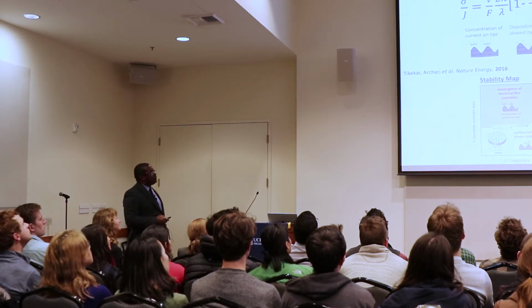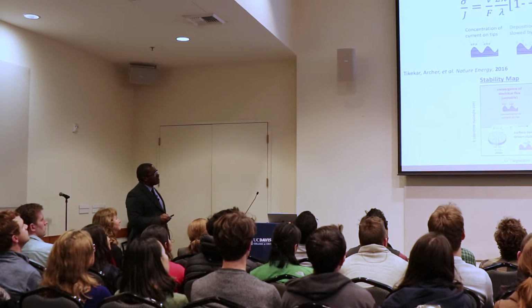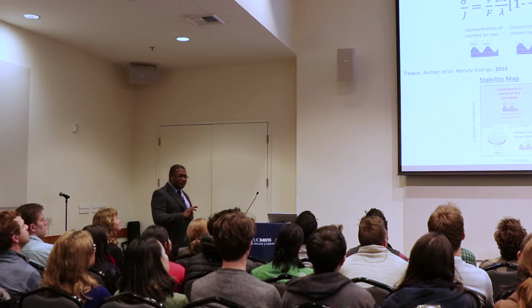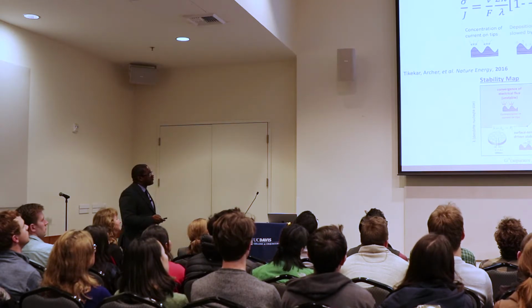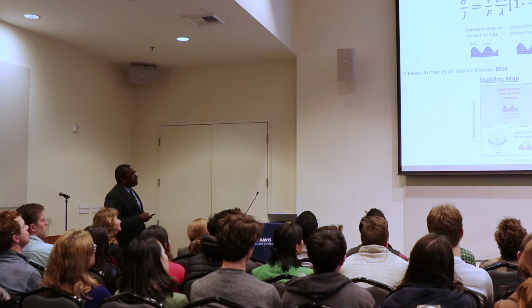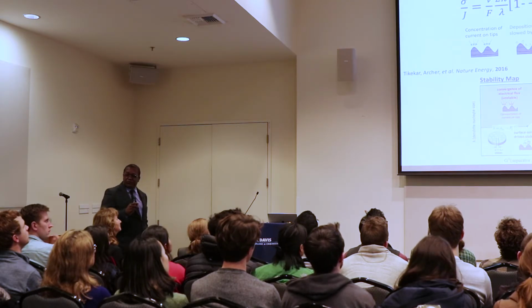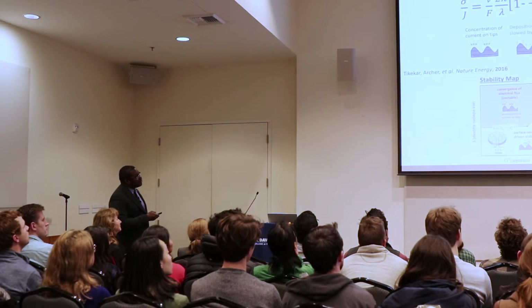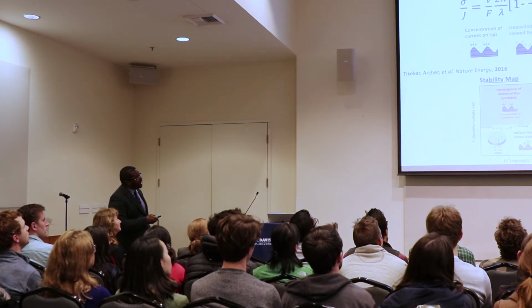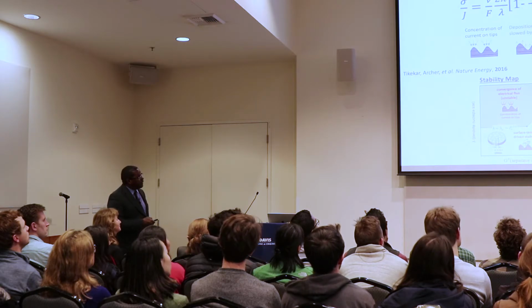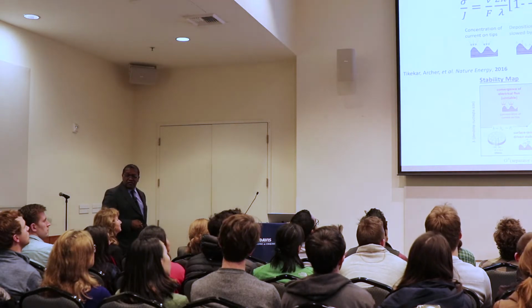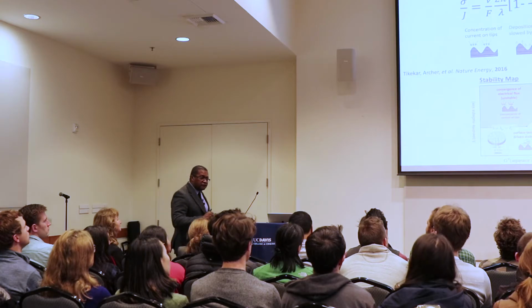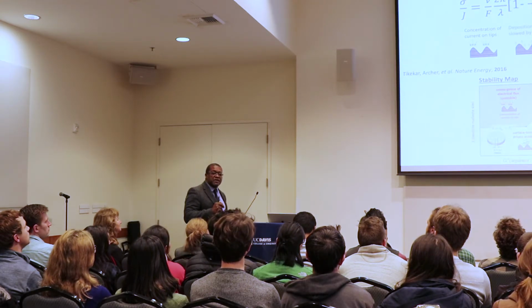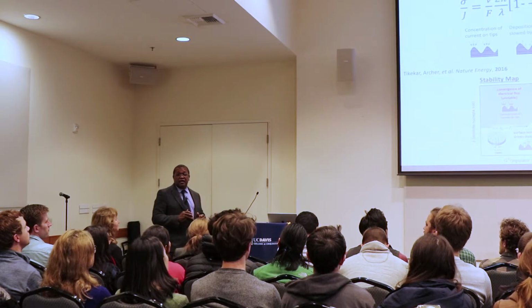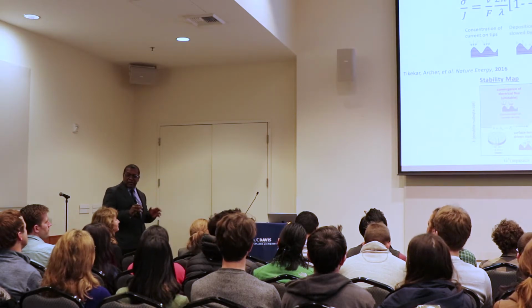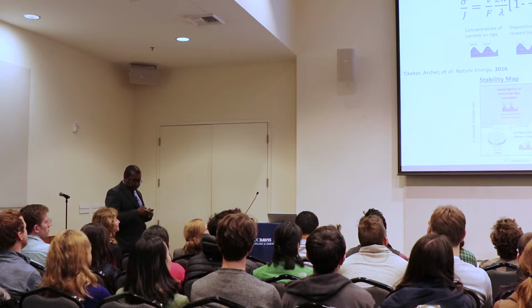What is cool from a chemical engineering perspective is that there are two dimensionless groups that describe everything. These two dimensionless groups, P1 and P2, have in them things that you might think might be important in this problem, like the modulus G, the transference number of the ions, the current density, the surface tension. These dimensionless groups tell us that, physically, this system is behaving like a normal continuum system, so you might have some hope of stabilizing it using normal continuum variables.